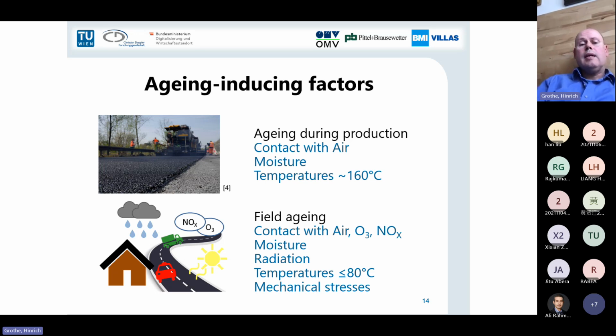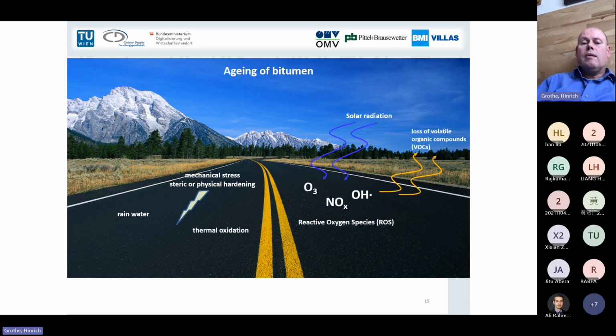That's the second process. And here we have a contact with air, but also with the reactive oxygen species like ozone, NOx, OH radicals. Moisture, of course, the sun radiation, temperatures of maybe up to 80 degrees. And there is, of course, mechanical stress due to the use of the road. So here we want to focus in particular on these reactive oxygen species, which you see on the right-hand side, and which are in an equilibrium also with the light and also with evaporation of volatile organic compounds.